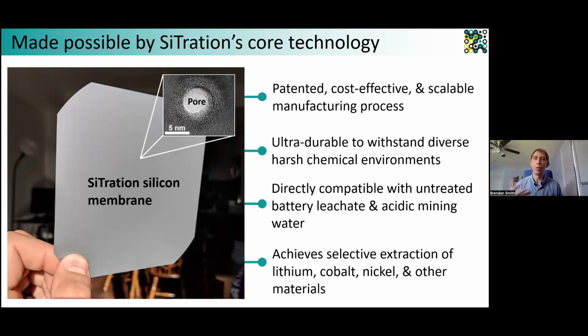So we simply dunk this whole thing in a chemical etch bath, which is based on water chemistry with acid. And what that chemistry achieves is to drill these tiny nanopores or micropores, essentially very, very narrow channels, from the top to the bottom of this flat silicon sheet, essentially composing our membrane structure.